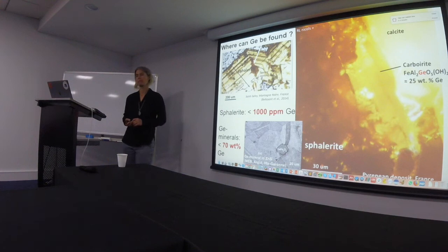It is very, very difficult to get down under about 50 microns, floating stuff out. And even then, that's a risk. One of the metallurgists, by the way, don't shoot me down in flames. I've just seen a lot of mines over my career, and they just can't do it. MacArthur River was a real funny one, because they struggled for years to make that work. And to get down to that level, you'd have to have a fairly rich ore body with primary minerals in it. The others would be a bonus if you ever got them out.